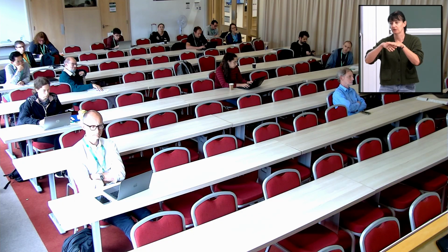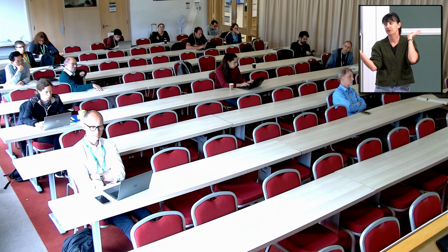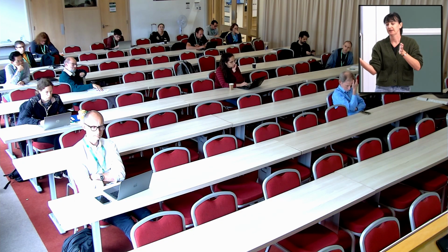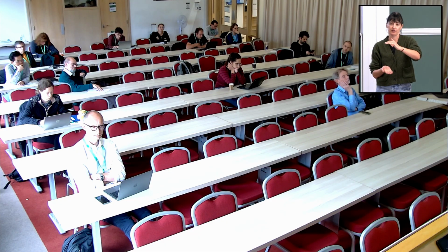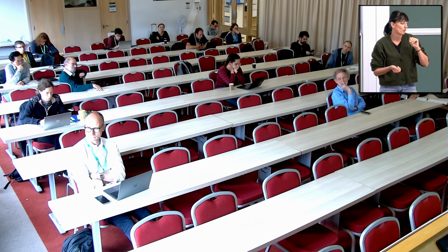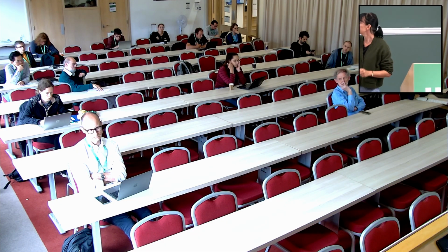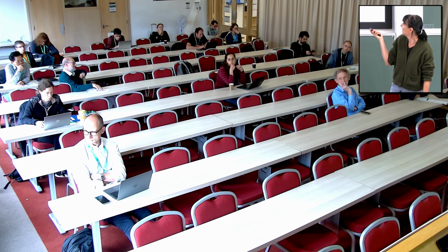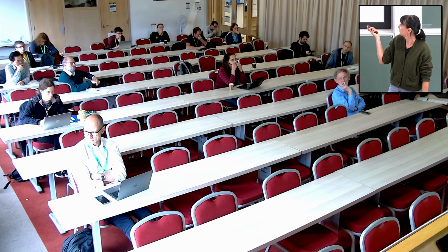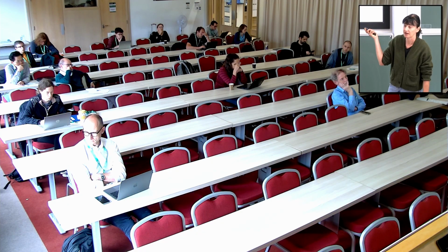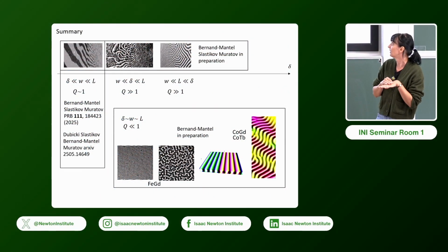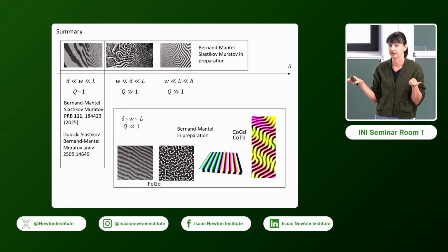Because the system in which you observe something very clean is an epitaxial system which is thick. When you go to a very thin epitaxial system, you have a lot of disorder that reappears. So this is this few-monolayer iron. And this is despite the fact that the system is supposed to be perfectly crystalline.